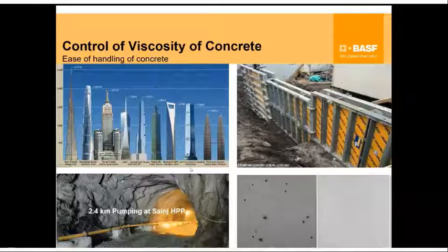And again, it's important that while you're placing the concrete after 1 hour or 2 hours, the concrete rheology properties, despite the thixotropy increase, is compensated by these molecules. Then it makes the pouring experience much better. Or for pumping concrete long distance, which has a whole range of other challenges, however, can be done by reducing, again, the viscosity of concrete. Lower viscosity of concrete can also give you better surface in general after you strip off your formwork. Next.